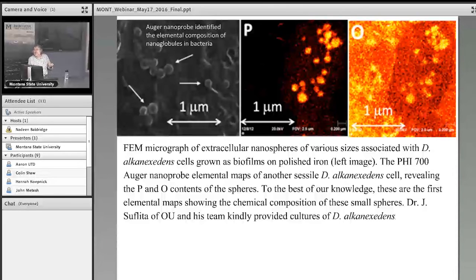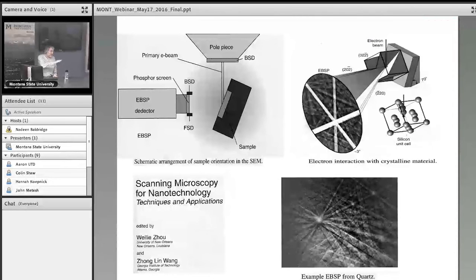I still have more. So how about the structure? There is what we call EBSD, electron backscatter diffraction. You tilt your sample, you shine the electron beam. There's a reason for that tilting. I'm not going to get into that. It's a very fundamental reason, actually. And then you have a camera here. You take pictures of a bunch of lines. These are diffraction lines. We call them Kikuchi patterns. There's the Bragg diffraction rule. And you see these lines.